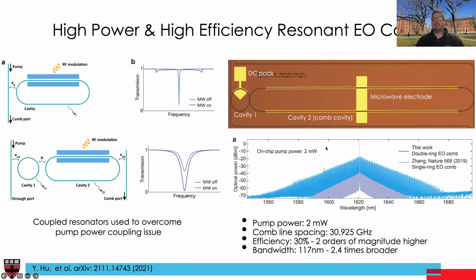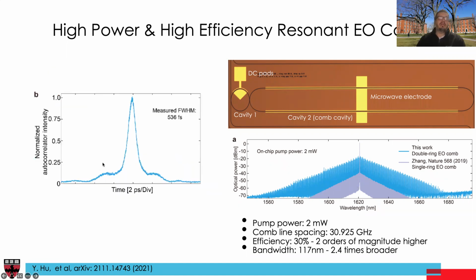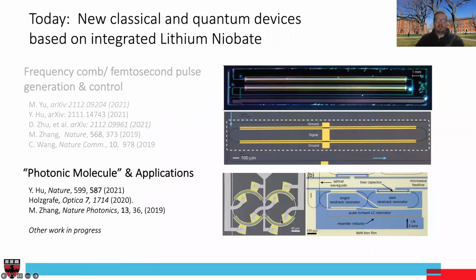And using this experimental data, he was able to show that compared to a single ring resonator comb, he can get a much broader spectrum with about 2 orders of magnitude more efficient comb generation and about 30% efficiency, which is unprecedented for a resonator-based comb. As I mentioned, it's on the order of a few percent, unless you're operating in the so-called dark soliton mode, but then the bandwidth of those dark soliton combs is not very large. So this is super exciting, and this also produces pulses on the order of 500 femtoseconds, and we also use this quite routinely in our lab as a benchtop comb source for some nonlinear experiments. This concept of coupled ring resonators, as I mentioned, we refer to as the photonic molecule concept, and I would like to tell you a little bit more about this and some other applications of this concept in the second part of the talk, which is going to be a little shorter.